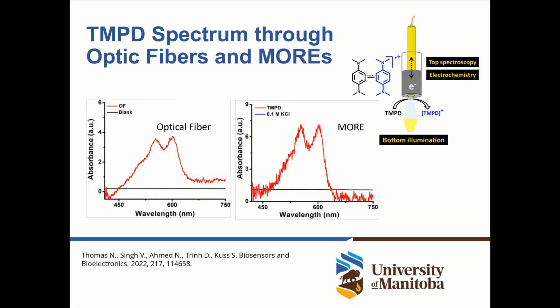And we have here the proof of concept for carrying out spectroscopy through these optical fibers. So we're using here again our TMPD because it has this characteristic blue color, and you can compare the spectrum collected through the optical fiber on the left to a spectrum that was acquired through our MORE. So this is still under investigation, and we are now hoping to be able to identify molecules that contribute to the electrochemical current signal by combining spectroscopy with electrochemistry.